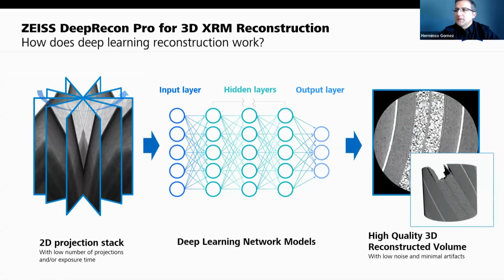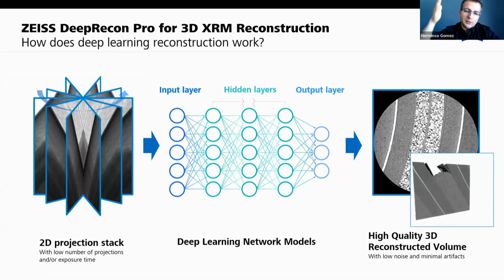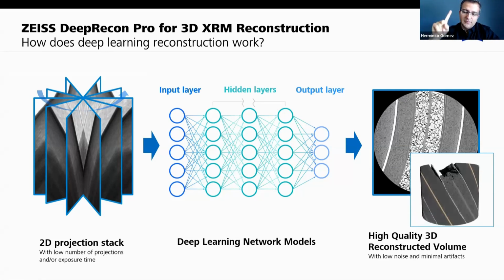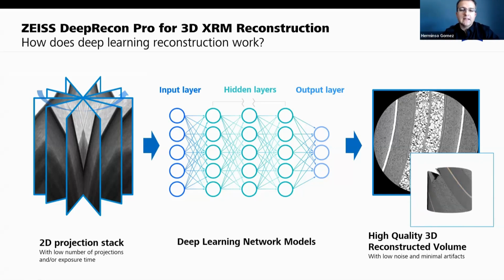It's basically a deep learning network model applied between the 2D projection stack, where the battery is rotating, you collect X-rays from different angles, and then you make a 3D reconstruction. When you use the classical way of reconstruction, the classical algorithms, which are analytical, you suffer from noise in the reconstruction. And the only way to partially solve that is to take a lot of projections, more than 2,000 projections or so, but that implies time.